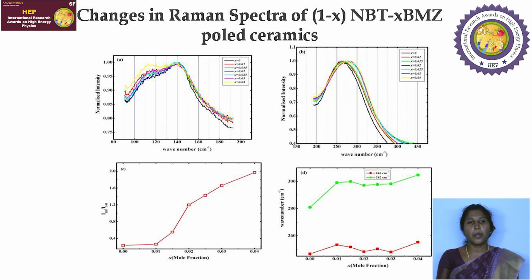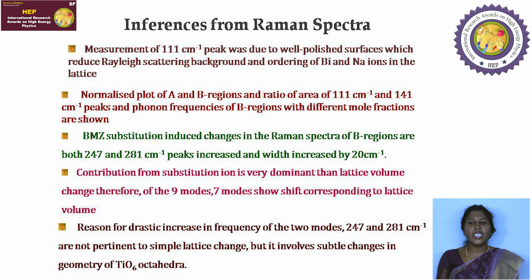In the A region as well as in the B region, due to the increase in the mole fraction of the BMZ substitution, there is a shift. You can't see much deviation in the C region and D region. In the measurement, at the 111 wave number (cm-1) peak, we can see the ETO1 mode due to the well polished surface, which reduces the Rayleigh background scattering, and the well ordering of Bi and Na ions in the lattice. So in the A region, there is a change in the frequency of the vibrations due to substitution, because of the polarizability of the substituted cations in the A site.